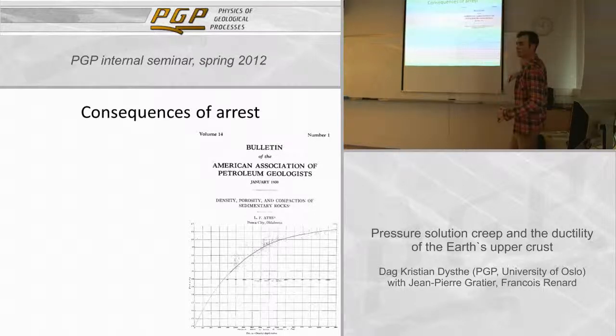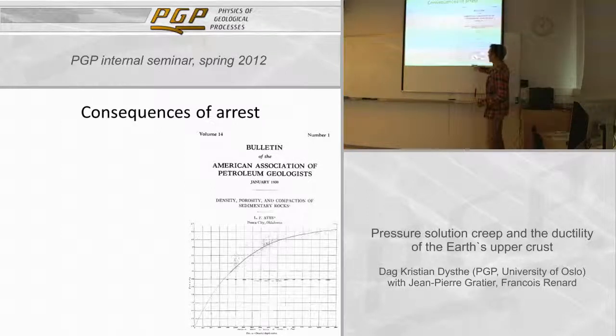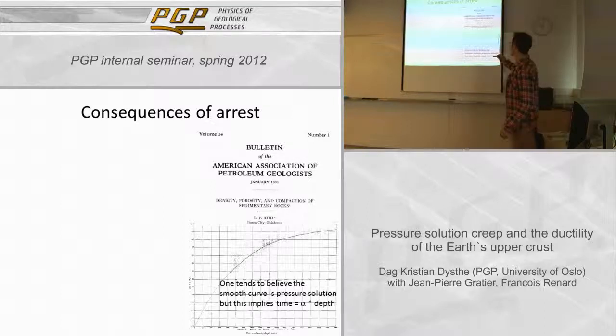This is density-depth curves from borehole logs in many different reservoirs. And after this, many people have been making correlations like this, where you see all these data plots that seem to show a trend, a mapping or a curve that relates depth to density. People have said that this typical smooth curve is due to pressure solution.